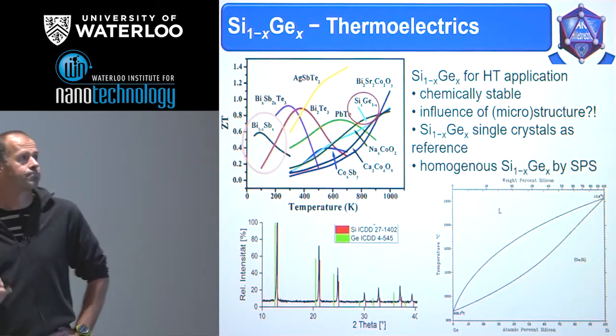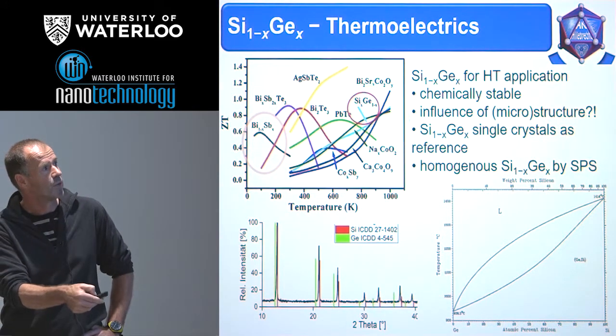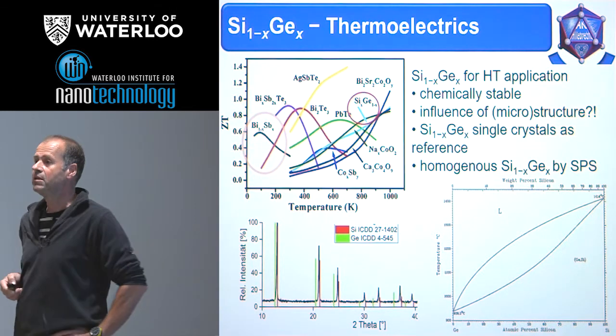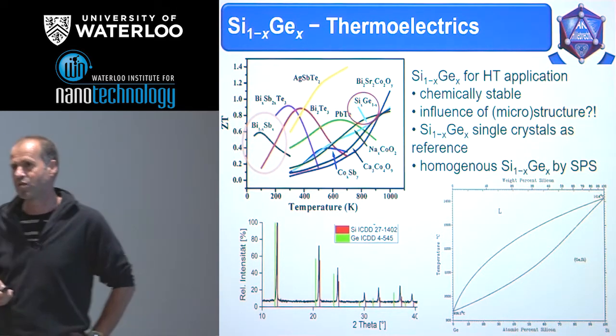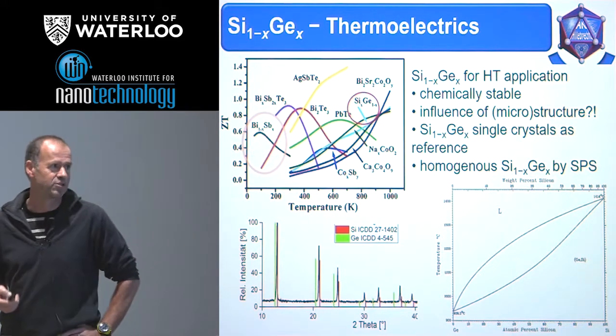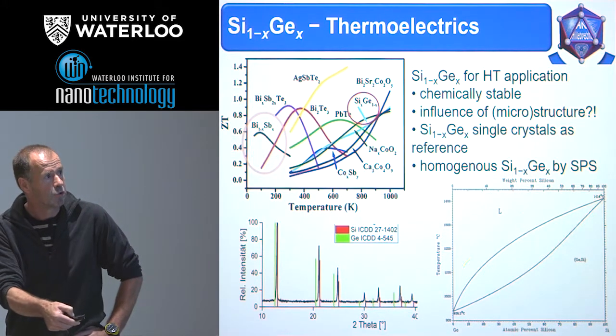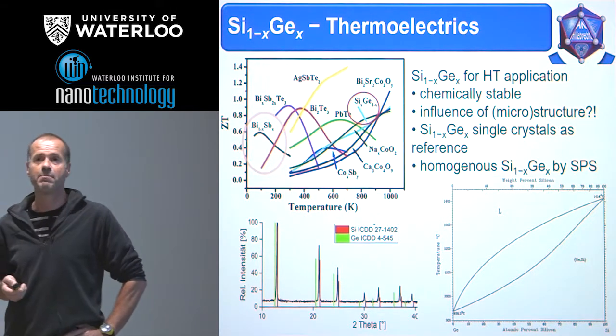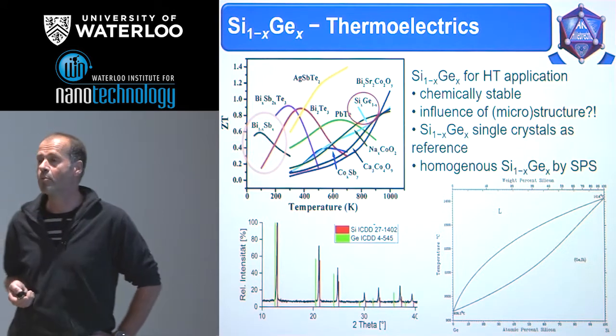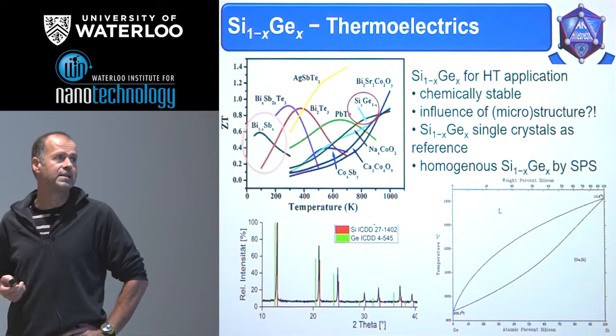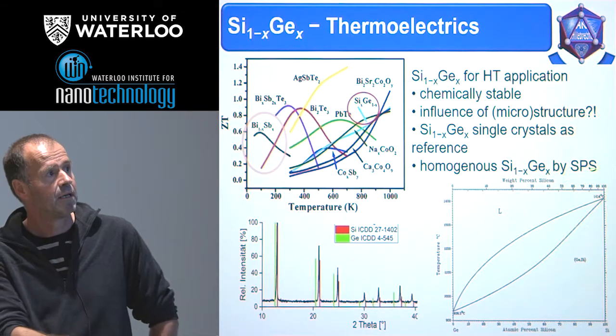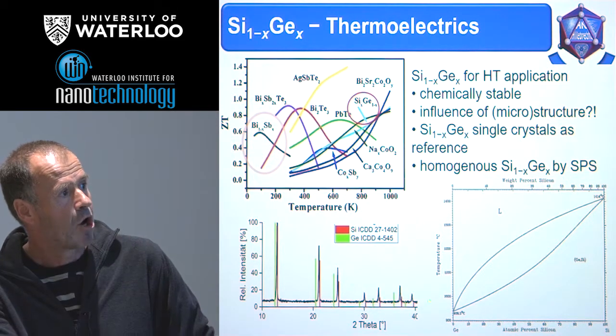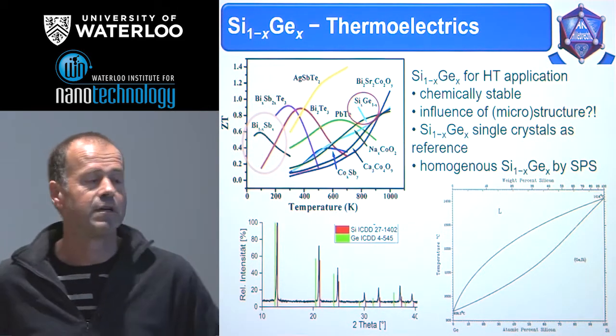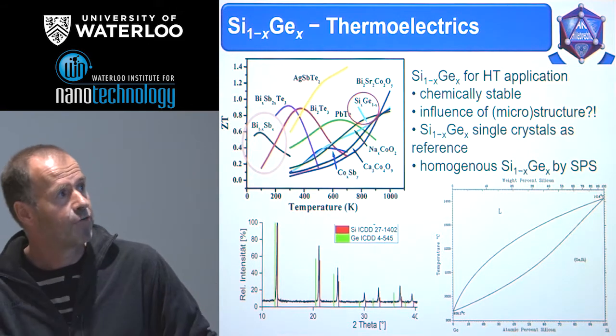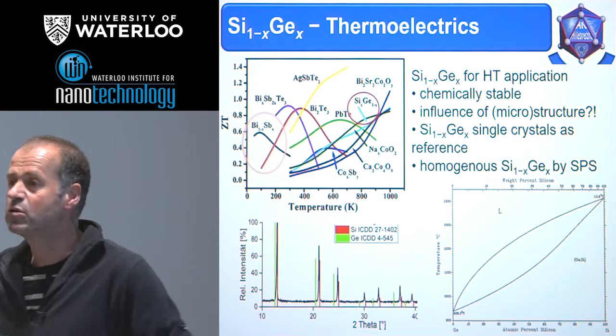Second aspect, high temperature materials. There's one system, silicon germanium, which is also structurally quite simple because it's the elemental structure. We see there is a solid solution between germanium and silicon, so it looks quite simple, but it is not easy to get homogeneous material. And by the application of our spark plasma sintering, we were able to get homogeneous material of the solid solution, and especially for the high temperature processes, it's not too bad.